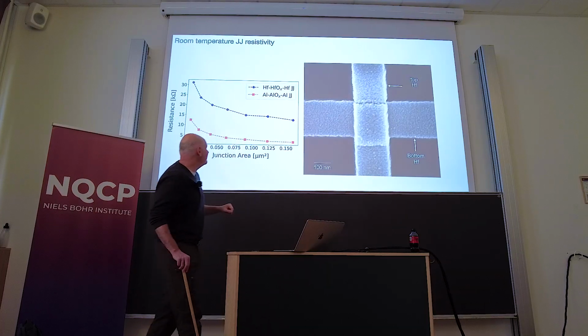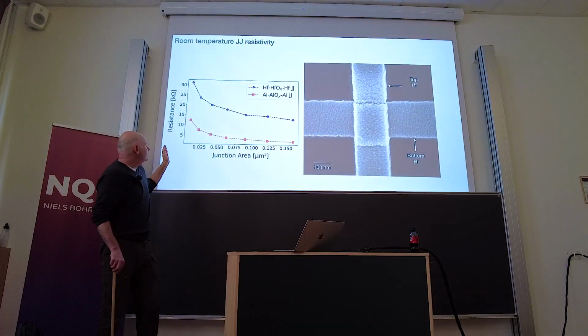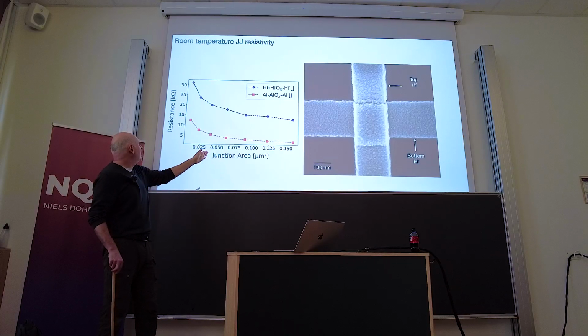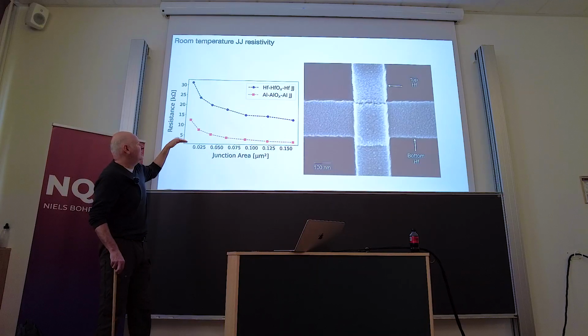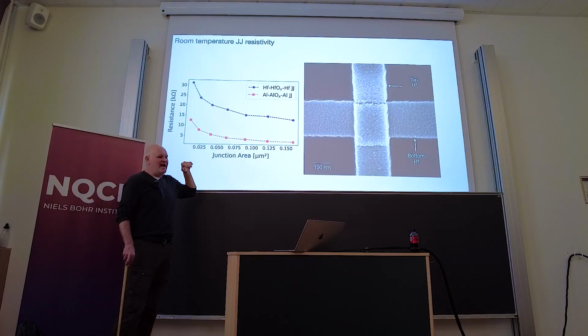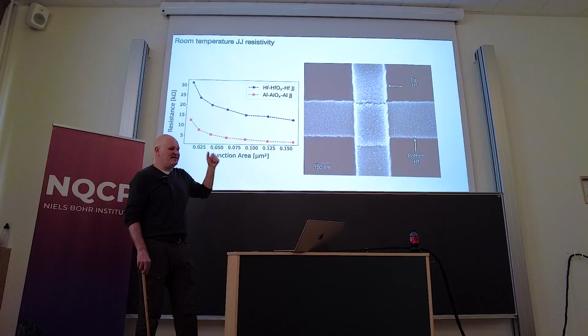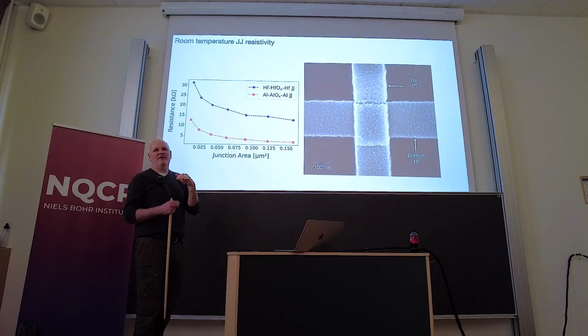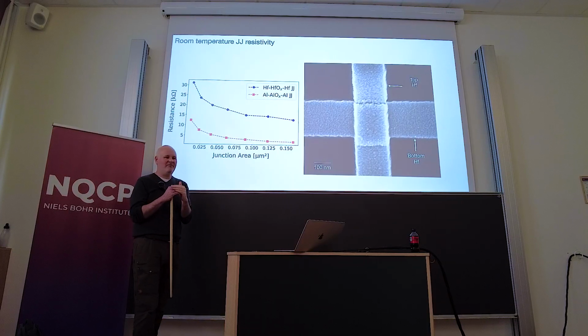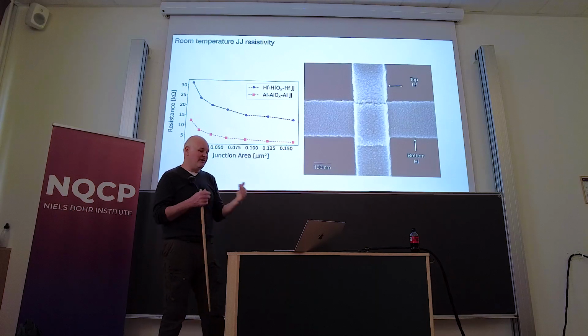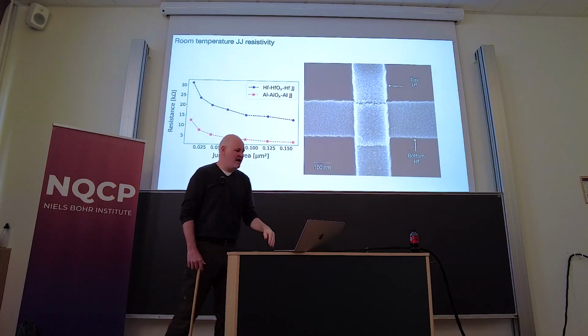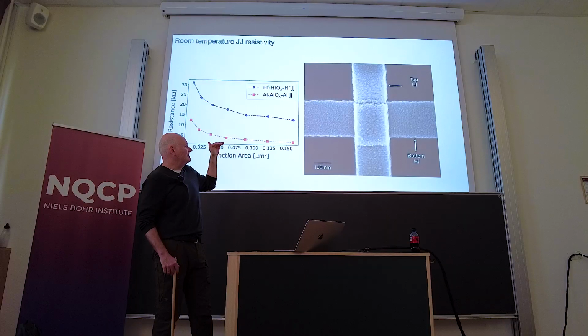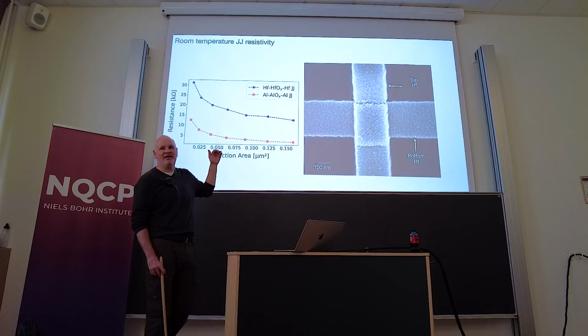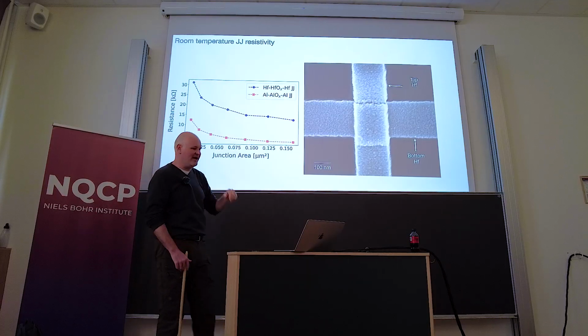There is something kind of interesting about these, is that if you look at the function of the junction area to the resistance, it doesn't match aluminum oxide well. And this is most likely due to either resistivity in the hafnium or a slightly incorrect thickness of the hafnium oxide, or just the hafnium oxide itself. But you can't scale the hafnium junctions the same way that you would the aluminum junctions. You have to understand that interaction.